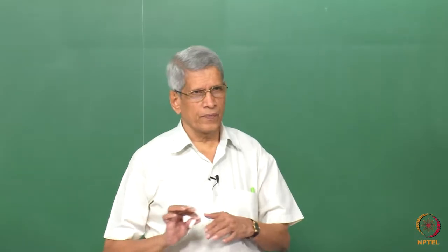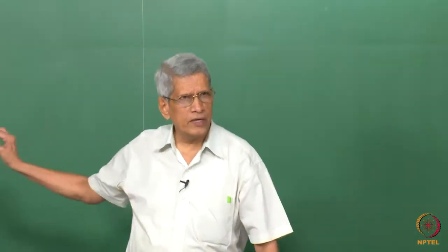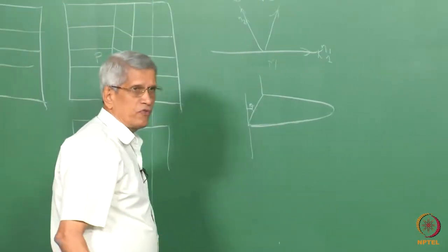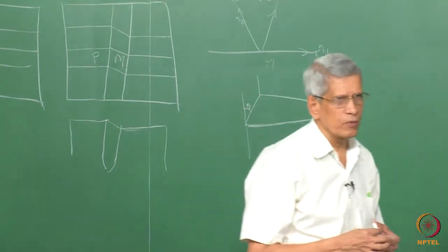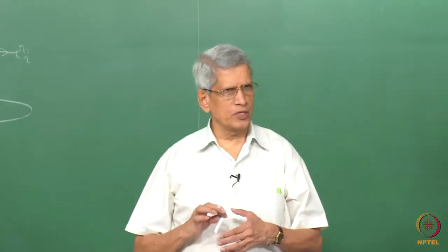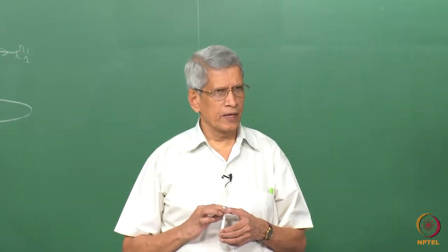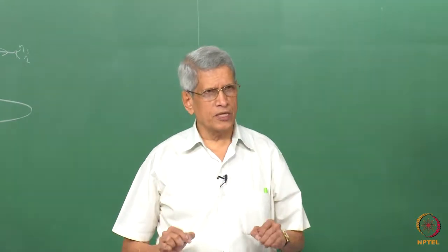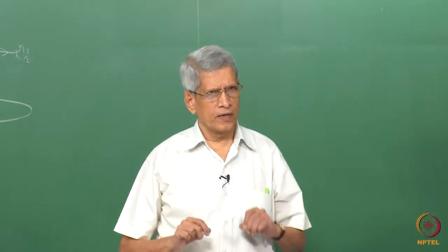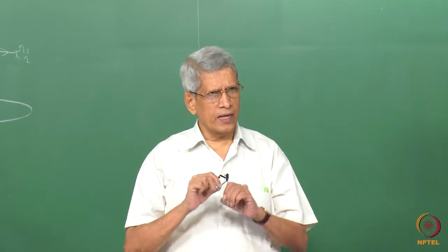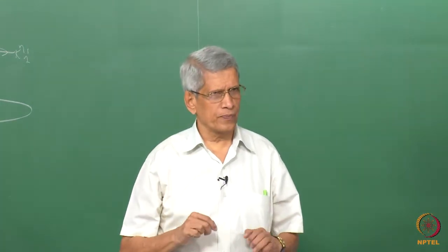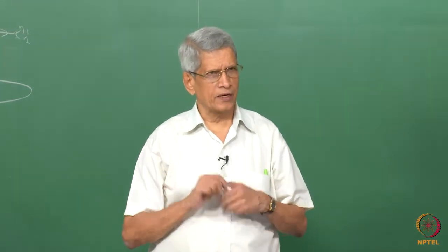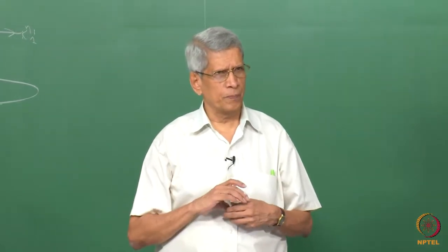Exactly the same theory can be used here. But the only thing which is important is that for twinning, we have looked at this theory, that is a simple homogeneous shear. Simple homogeneous shear can be considered as giving an elongation in one direction to a volume of a material and then a compression in a perpendicular direction which is equal and opposite to it.